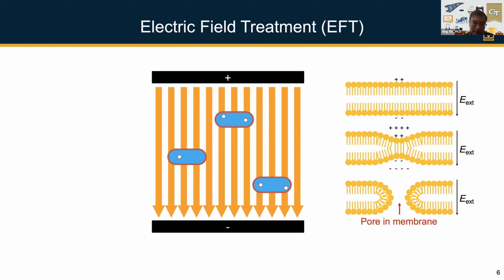But the real challenge is that to realize a strong enough electric field, even for the normal reversible electroporation process, you usually need to apply several kilovolts, because the electric field strength is defined as the voltage divided by the distance between the electrodes, right? For biomedical applications, usually they use small cuvettes, and the distance between the electrodes is usually on the millimeter scale, which is already very small, right? And then you still need to apply several kilovolts of voltage.